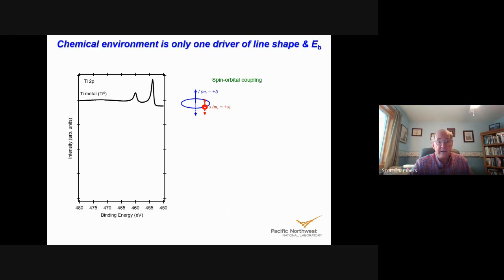And so spin-orbit coupling happens because the orbital angular momentum of a core electron and the spin angular momentum of that same electron can couple either parallel or anti-parallel. So here's the parallel arrangement, and here's the anti-parallel arrangement, and they have different energies. The parallel arrangement is rather unfavorable because this is a relativistic effect, and so this state where you have L plus S for the J total angular momentum is going to be of lower binding energy. Whereas if you have the anti-parallel arrangement where you have L minus S, this is more favorable. It'll have a higher binding energy. So in this case, of course, L is equal to 1 and S is equal to 1/2. So we have J equals 1/2, which is the higher binding energy peak, and we have J equals 3/2, which is the lower binding energy peak. So that's spin-orbit coupling, and it's always there.